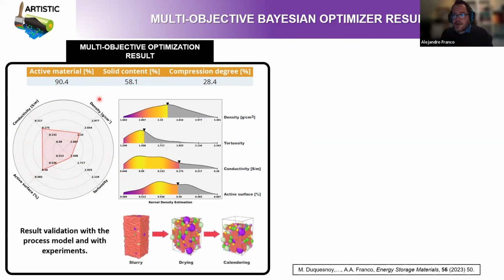And if you enter these manufacturing parameters in the manufacturing simulator, and then you characterize the electrode properties of the resulting virtual electrode, you will realize that these properties match very well with the predictions of the Bayesian optimizer. So this is a way of validating the prediction of the Bayesian optimizer. And this is something that we have also performed at the experimental level. So we have checked that this electrode can be made at the experimental level by entering these manufacturing parameters predicted by this Bayesian optimizer.